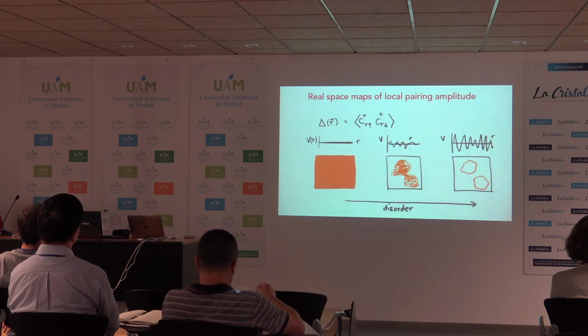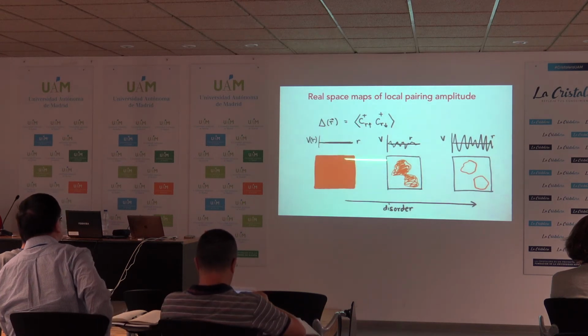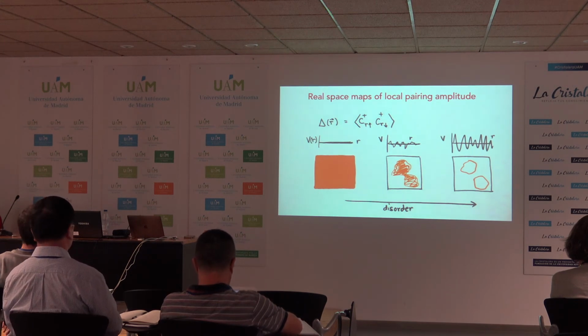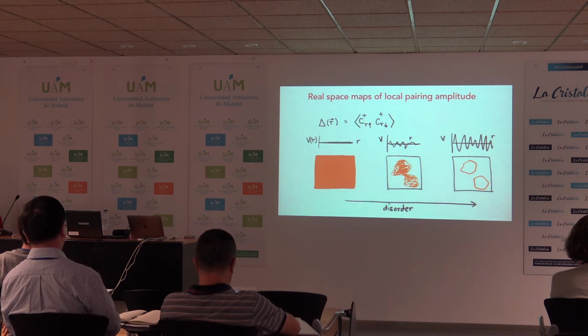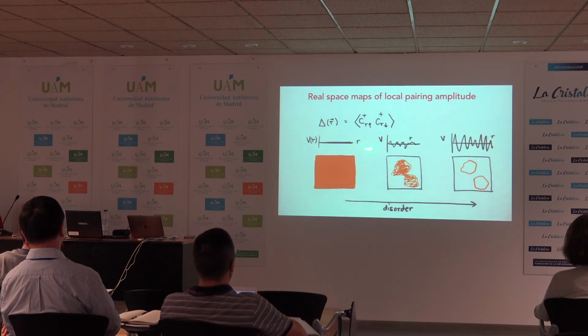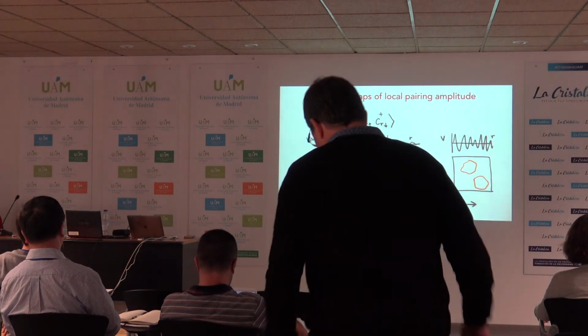Okay. So this is what we find. The focus is going to be on getting the real space maps of the local pairing amplitude. I use my words now very carefully because all of these different scales, which were very similar in the BCS theory, start to become different. So this is the local pairing amplitude. And when there's no disorder, of course, it will be homogeneous, the same everywhere. When I put some random potential and I take some profile, I'll show you that the map of this delta of R starts to show this inhomogeneity.